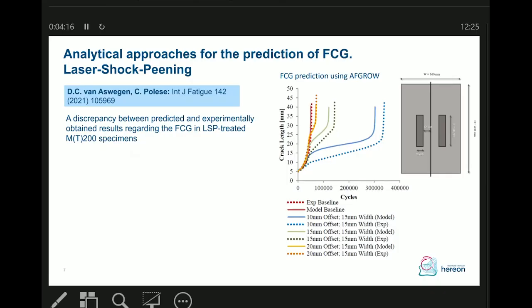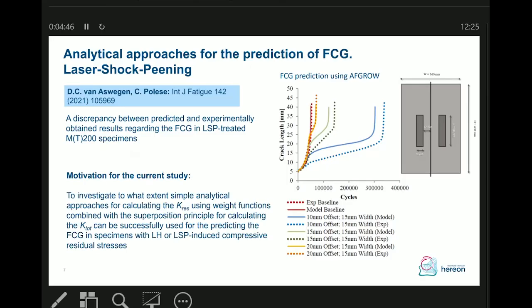In such software, typically residual stresses are accounted for using the weight function method. There are some publications where it was investigated if we model the fatigue growth of a specimen with residual stresses introduced, for example, using the laser shock peening process. And you see here there is some disagreement. Therefore the motivation for the current study was to investigate whether we can successfully model fatigue growth using the weight function approach, and as application cases, we investigated both processes, laser heating and laser shock peening.